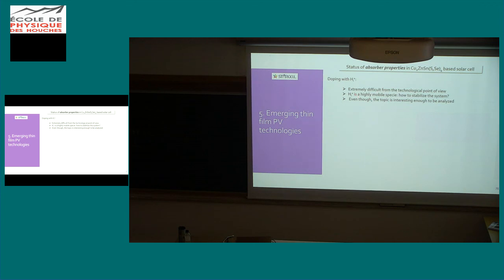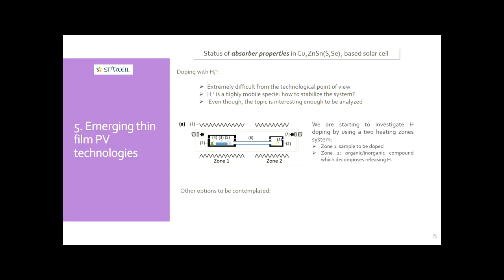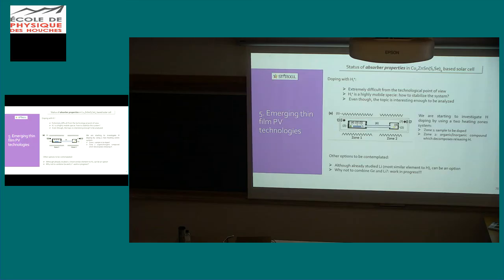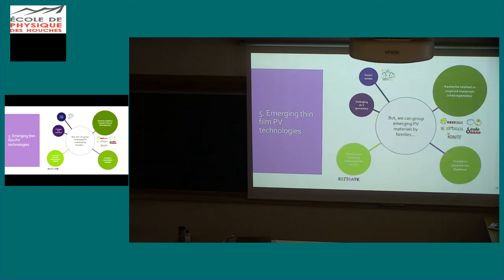And with hydrogen, the problem is it's extremely difficult to dope with hydrogen. Hydrogen is a highly mobile species and it's very difficult to stabilize. So this topic is very interesting and we are starting to introduce some strategies to try to prove that with hydrogen doping, it could be possible to improve kesterite. Although we have some evidence in the literature because some of the most efficient devices on kesterite were doped with lithium, and lithium is very similar to hydrogen. So the introduction of lithium can somehow be similar to the introduction of hydrogen.